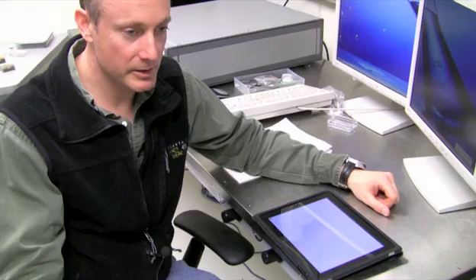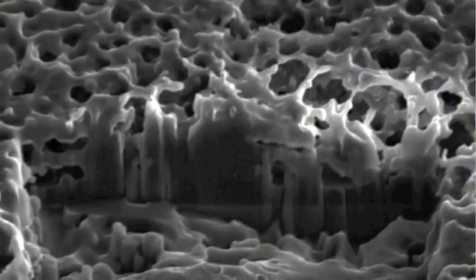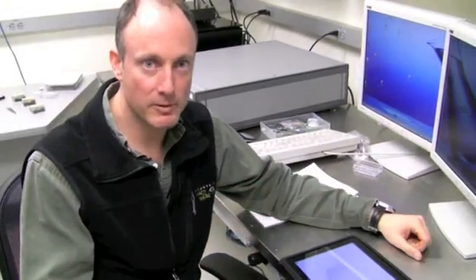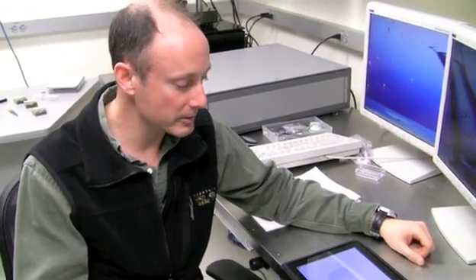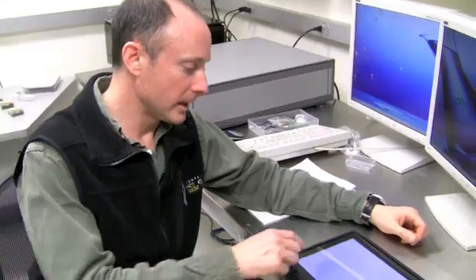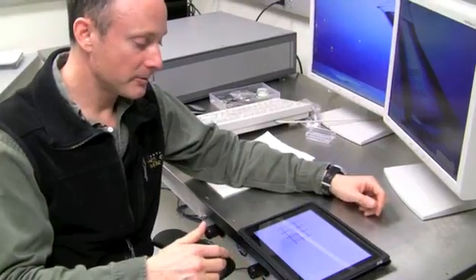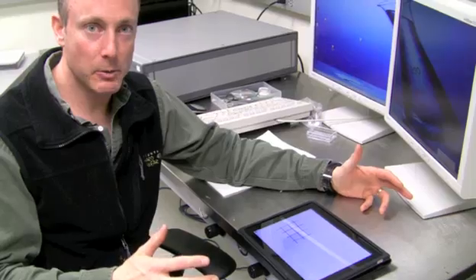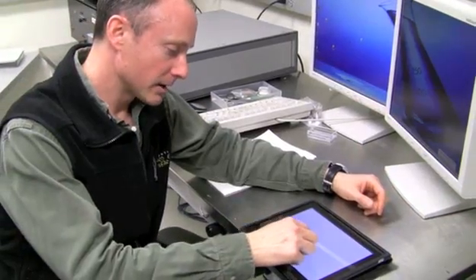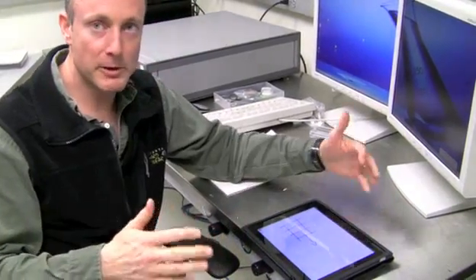In the image, what you see is essentially inorganic cobalt oxide nanowires that were synthesized on top of a three-dimensional mesh network of virus that are all cross-linked to one another. We envisioned initially an idealized three-dimensional mesh network, essentially arrayed orthogonally or at 90-degree angles in 3 dimensions. If you relax that requirement for 90 degrees and accept the fact that our virus is a little bit flexible,